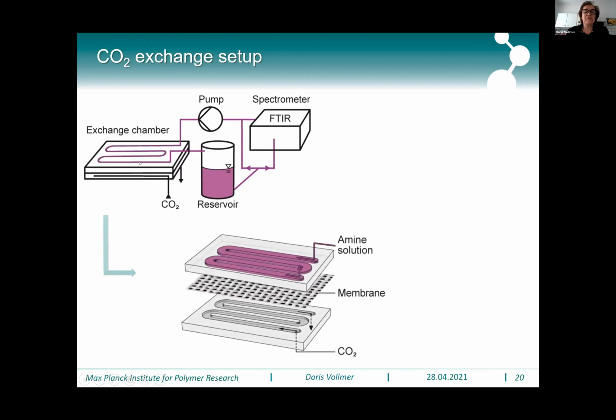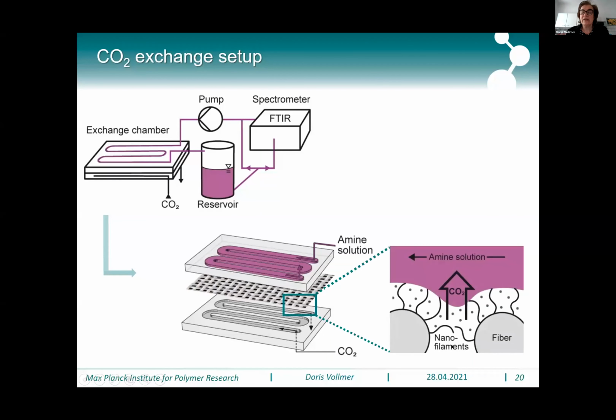At a higher magnification, our exchange chamber looked like that one. So we have here our amine solution flowing over the membrane. Here is the membrane, and at the lower side of the membrane, we have our carbon dioxide. Now, because of the air cushions, the carbon dioxide can easily diffuse through the membrane into the amine solution.